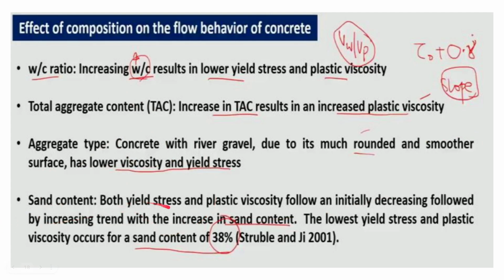And sand content: both yield stress and plastic viscosity follow an initially decreasing, followed by an increasing trend with the increase in sand content. So this has to be kept in mind. The lowest yield stress and plastic viscosity occurs for a sand content of 38%, as per Struble.